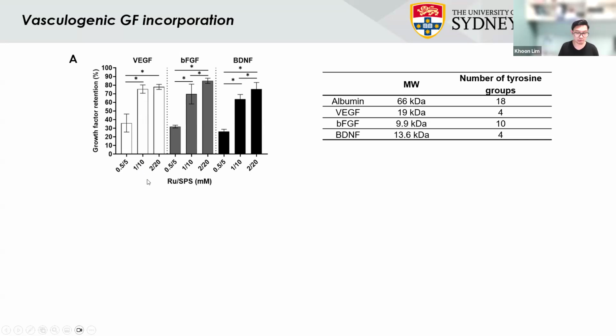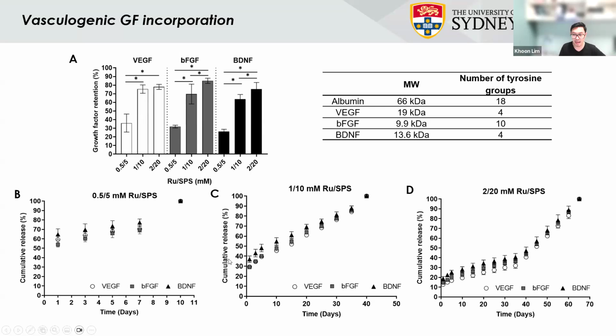With more photoinitiators, of course, you have more of these growth factors covalently bound within the system. And you can see then when you start culturing them just in media, as the hydrogel itself is slowly degrading, you are releasing the growth factor. So low photoinitiator concentration, slowly increasing over time. And you can see that the release profiles go from about 10 days to 40 days to about 70 days. So very much covalent incorporation, depending on the dityrosine bonds that we are now imparting due to the visible light photoinitiating system. And as the hydrogel backbone itself is degrading, we are slowly releasing these factors.